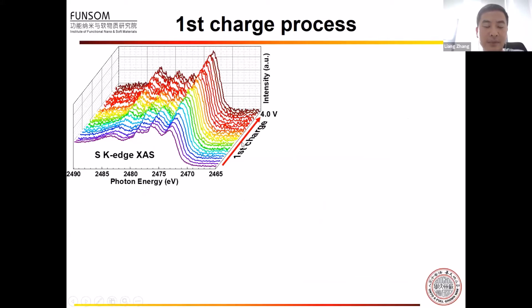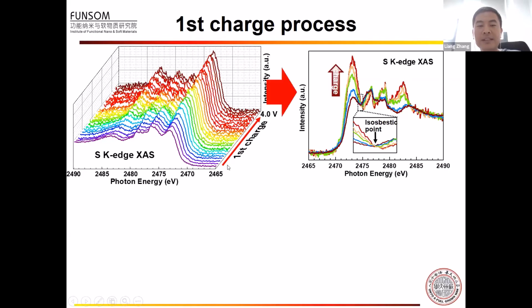This is the result for the first charge process, and from bottom to top is the charge process. We can clearly see a very apparent change for the main feature, and its intensity is gradually increasing. However, we didn't find any pre-edge feature related to the lithium polysulfide, which should be around 2470 eV. This result indicates that during the first charge process, no lithium polysulfide is formed. In addition, we find an isosbestic point in the stack plot of sulfur K-edge spectra. This result indicates the first charge process is like a two-phase conversion reaction.